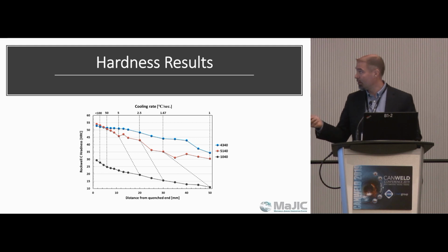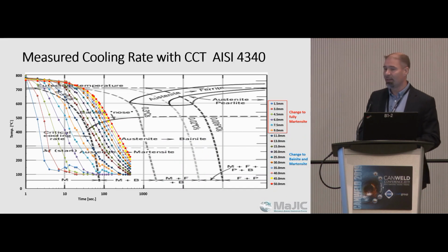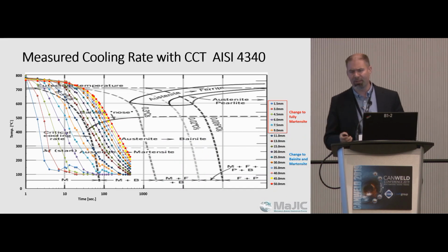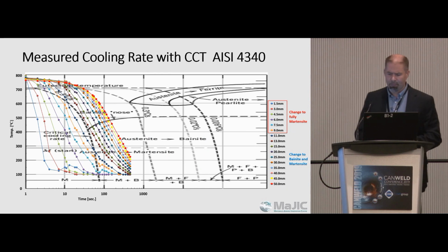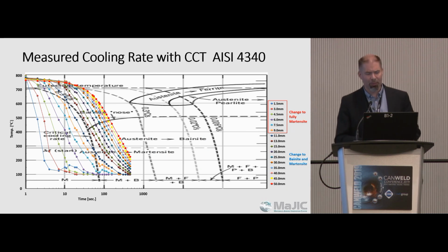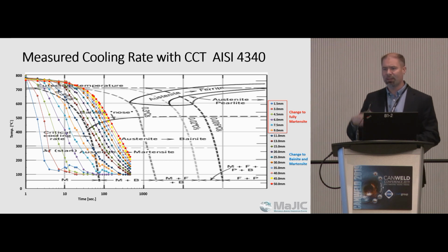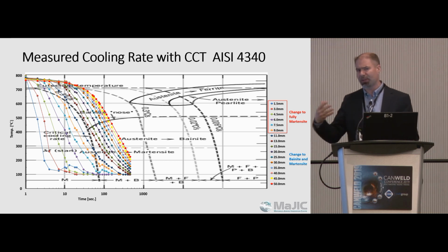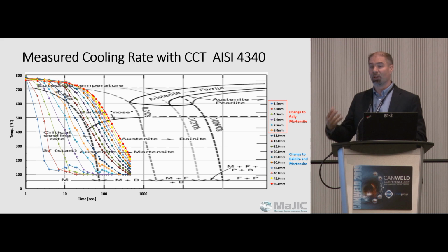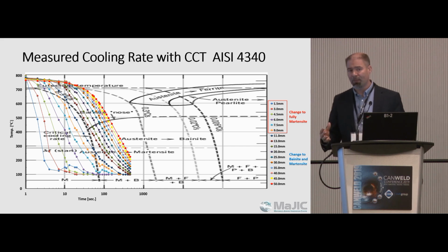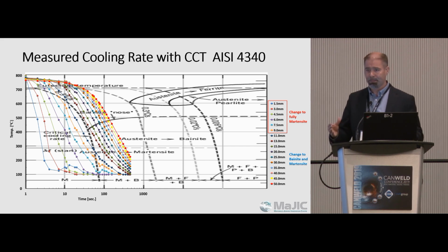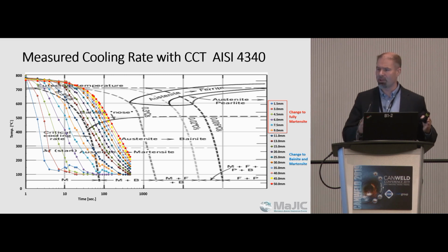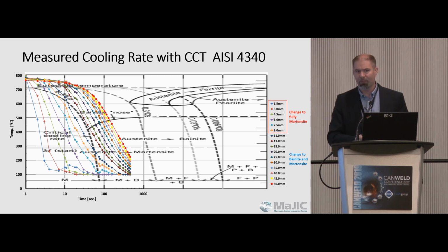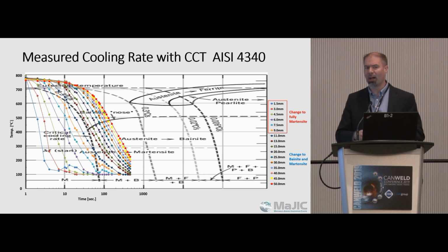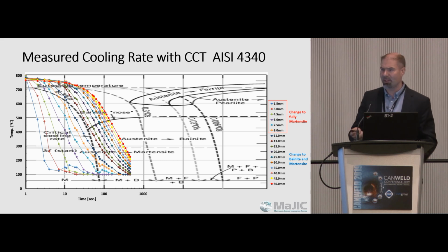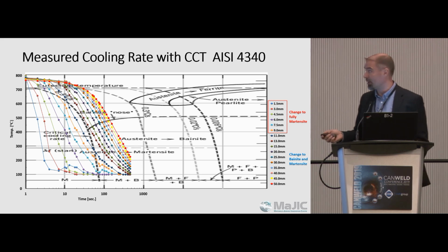Now, we look at some of the, again, very busy graphs. So, the continuous cooling transformation diagram. Again, we need to take these things with a grain of salt. In this particular case, with a Jominy end quench, we've got lots of time for austenite to form. So we don't need to worry too much about some of the issues of not fully transforming to austenite that we see in weld metals in the heat affected zones.